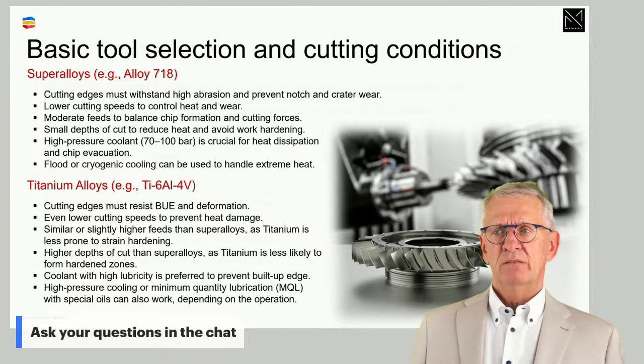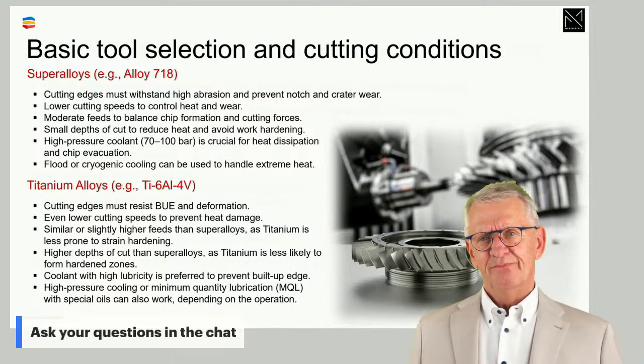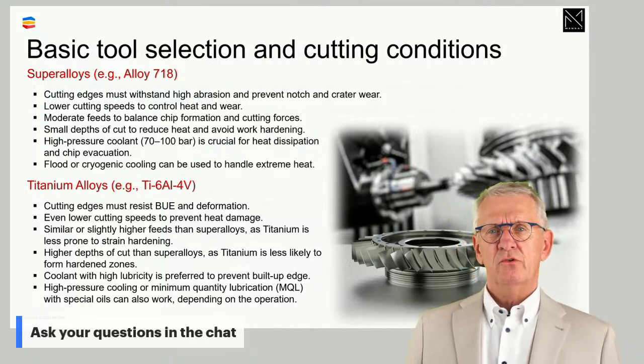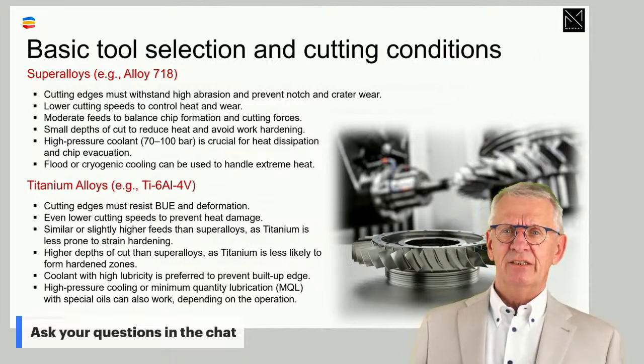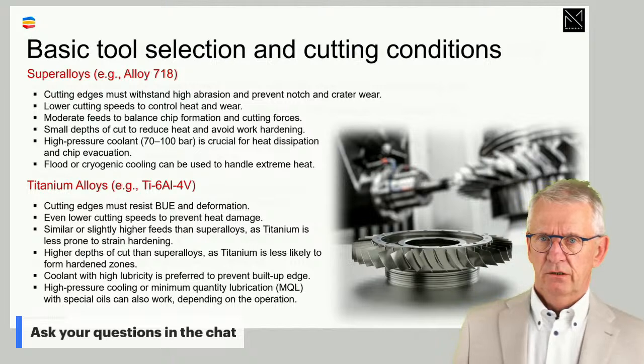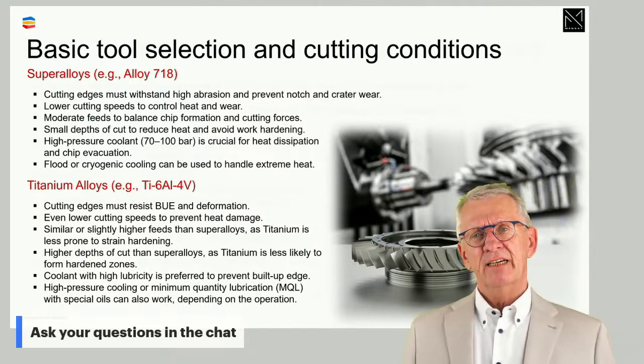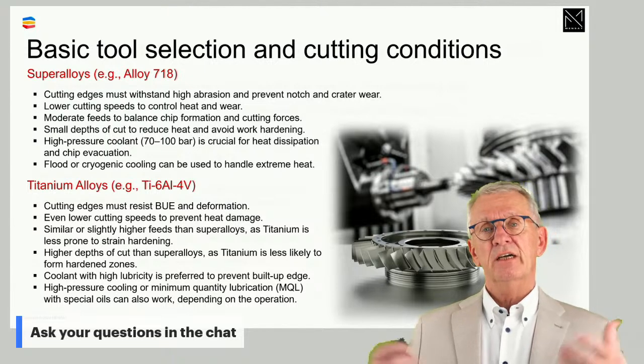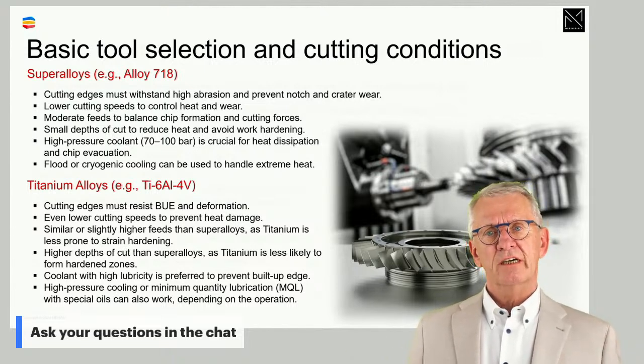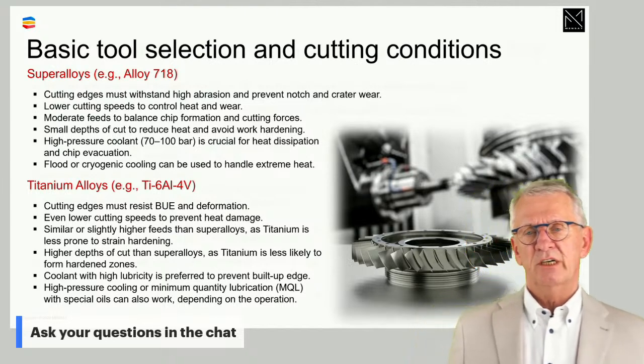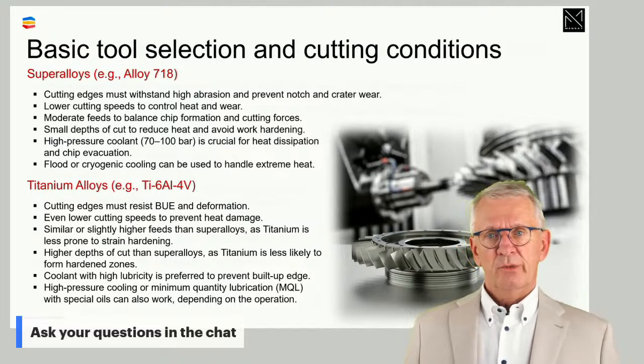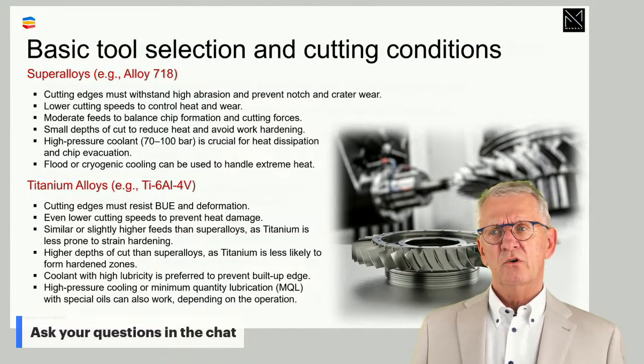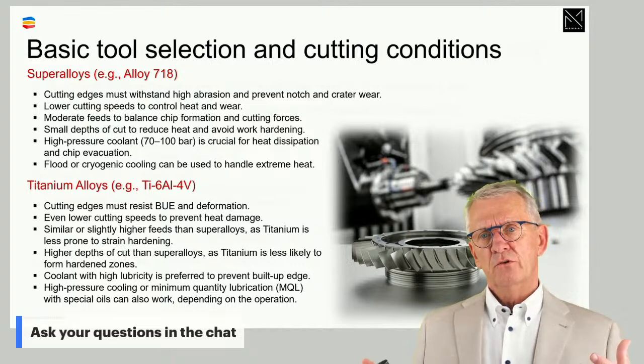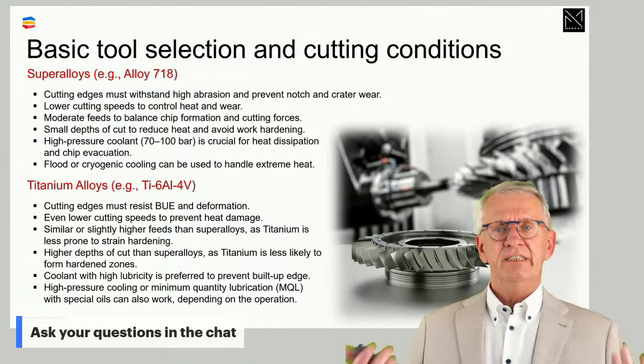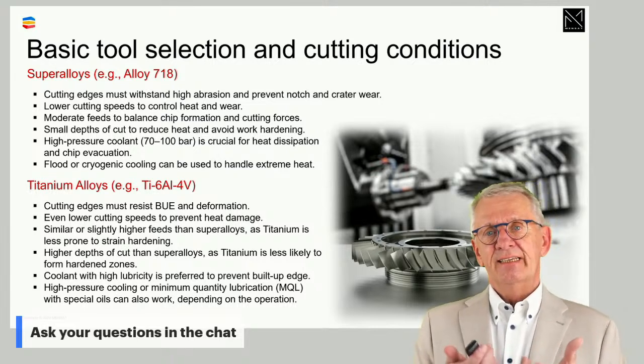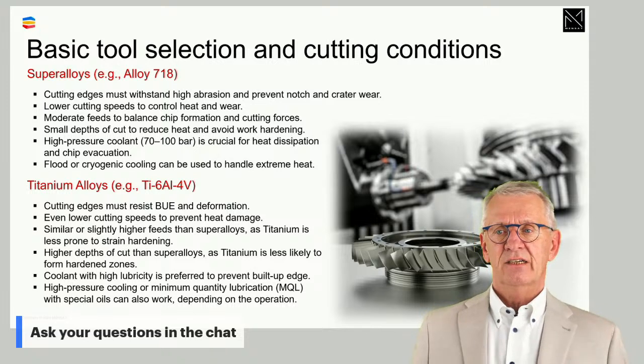Feeds, superalloys, moderate feeds, not too small, not too high. In titanium, normally we can use higher feeds. It's not going to give mechanical problems when we use very high feeds. In superalloys, you have to be more careful with that. Depths of cut in titanium, take them as big as possible without deforming the workpiece and that type of stuff. In superalloys, you have to be a bit more careful again, because if you go for bigger depths of cut, you are going to generate more heat, which is part of the game then, and yeah, you have to handle that.